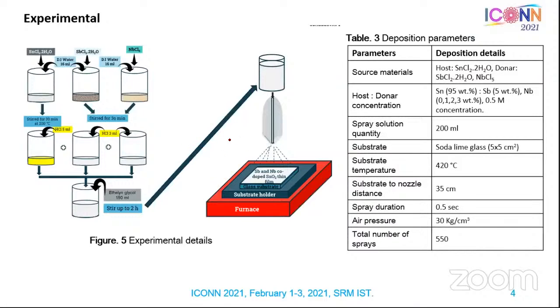Coming to the experimental part, we followed the sol-gel method. First, we collected all the chemicals individually. Then we stirred the individual chemicals. After dissolving properly, we added some HCl to dissolve more and to get a transparent solution. After getting all the transparent solutions, we filled them into one beaker. Then that solution was again mixed with ethylene glycol, and that solution was loaded into the spray unit.